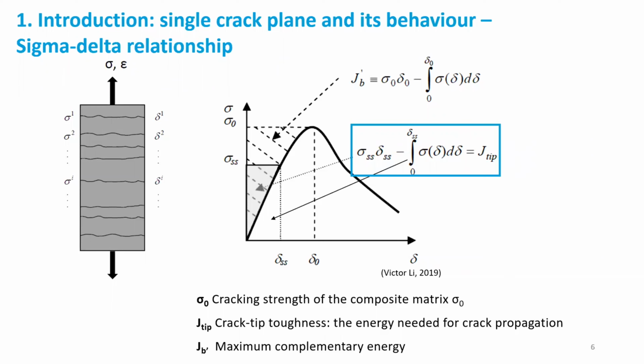To further assess this steady-state cracking, we have to check the single crack plane and its behavior, which could be characterized by the sigma-delta relationship, in other words, the fiber bridging stress versus crack opening width relationship. As shown in this figure and the equation, the total work on the crack body is consumed partly by the crack bridging as strain energy, and another part is consumed by the crack tip opening during crack propagation, which corresponds to here, the J tip.